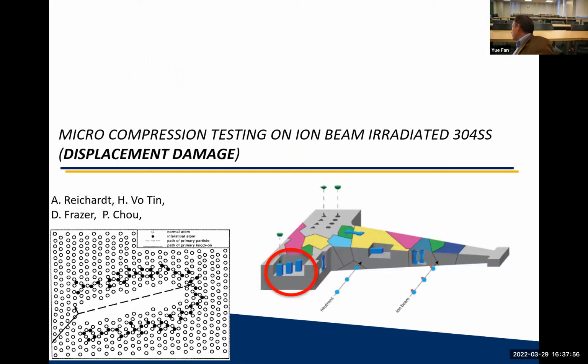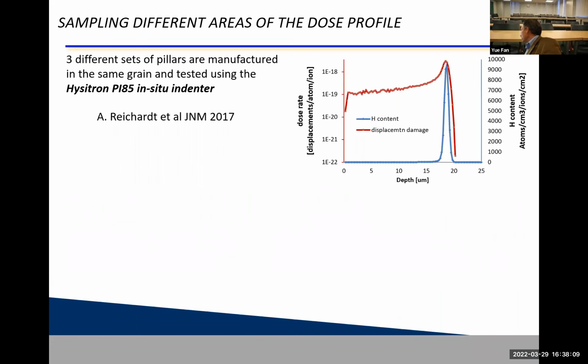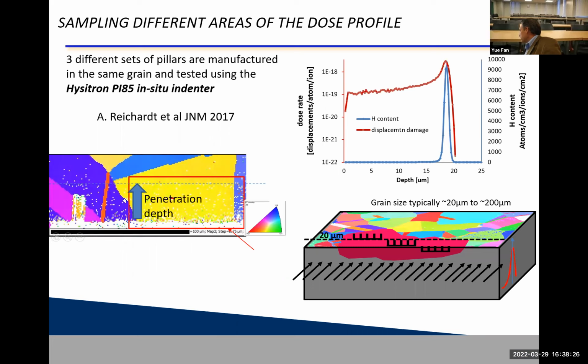So as the first case, I would like to talk about radiation damage in 304 stainless steel. In fact, that sample has been irradiated here in Michigan and was studied in Berkeley. So it was irradiated with 2 MeV protons, which penetrate about 20 microns deep into the material. Here's the dose profile shown, and where the protons end up at the end. And so 20 microns is all the material you have to work with. The beam came from this direction, this is how deep it penetrated. And we looked for a large grain, which can accommodate many, many mechanical test samples. So each test pillar in this instance is in the same grain as its neighbor, so orientation doesn't play much of a role in this instance. And the nice thing also is if you put your mechanical test samples beyond the penetration depth, then it's unirradiated, and so you can sample different doses along the way.